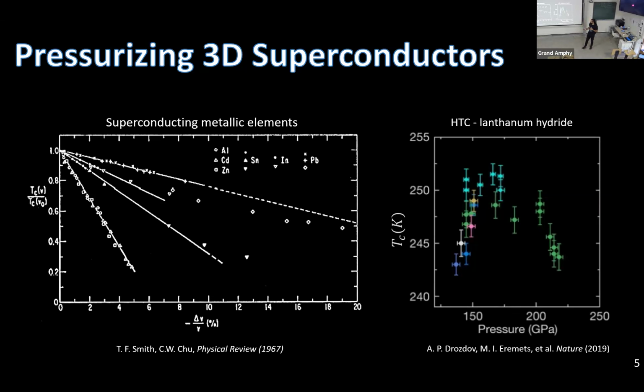We have here a graph of normalized critical temperature as a function of pressure for multiple superconducting metallic elements such as lead, indium, tin, and more. As you can see, as they increase the pressure on those superconducting elements, the critical temperature decreases, which indicates again that pressure destroyed the superconductivity in those materials. This effect was explained by the fact that pressure reduces the density of states in those materials, and if you are reducing the density of states, you're destroying superconductivity in the sample.